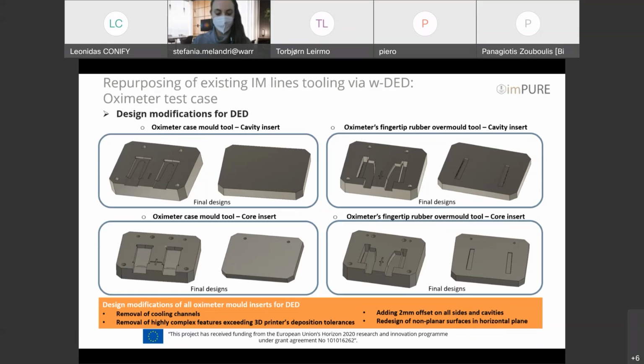Depending on the additive manufacturing technology applied, or the system, there are certain limitations, as in every manufacturing method. In this case, we had to remove the cooling channels, and remove some highly complex features that exceeded the 3D printer's deposition tolerance. We had to add a couple of millimeters offset on all sides and cavities to ensure there is enough tolerance for machining later on. And we had to redesign some of the non-planar surfaces in the horizontal plane. We were limited because of the wire diameter, of course, so there are technical specifications that might limit the accuracy and the resolution of some of the builds. So next slide, please.